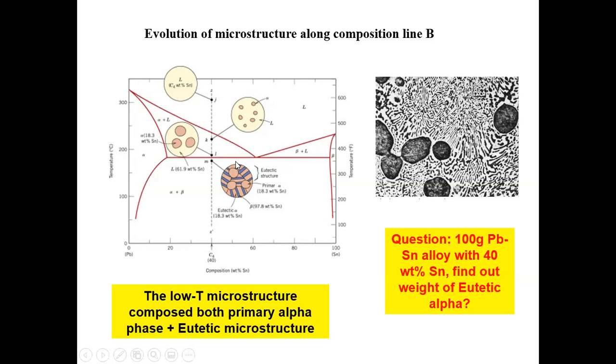And when you get these 2 arms, you get the relative fraction of the 2 phases, and because you have 100 grams of overall alloy, you can compute the actual mass of the liquid phase and the actual mass of the alpha phase, right? Does this make sense to everyone? Using this particular point and the lever rule, does this make sense? This is very important. Yes. Okay. And then you move on, right?